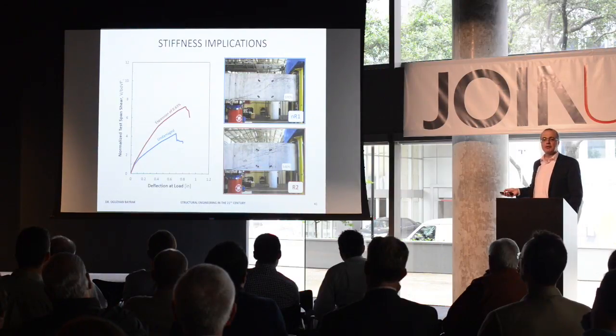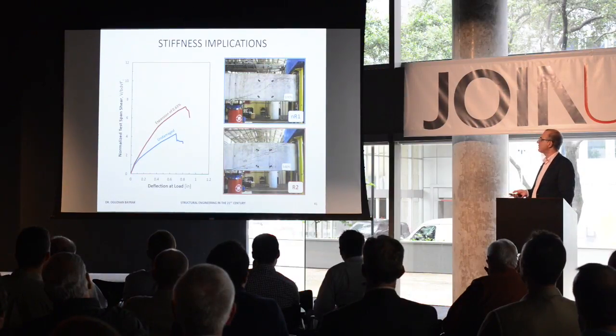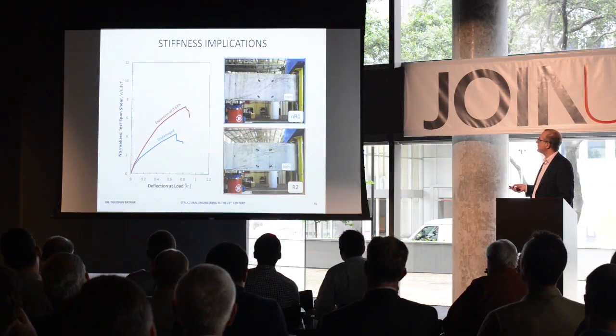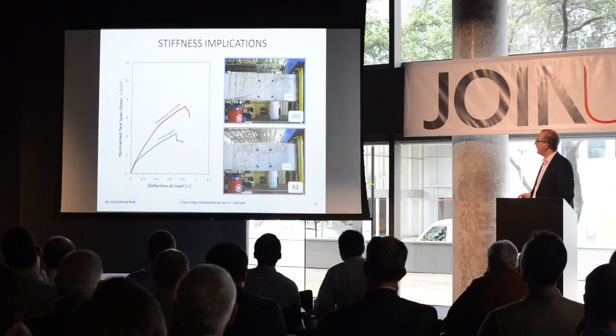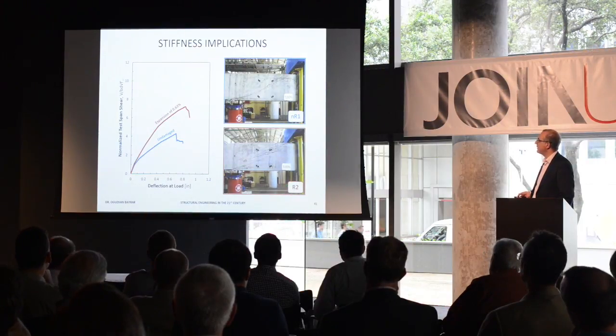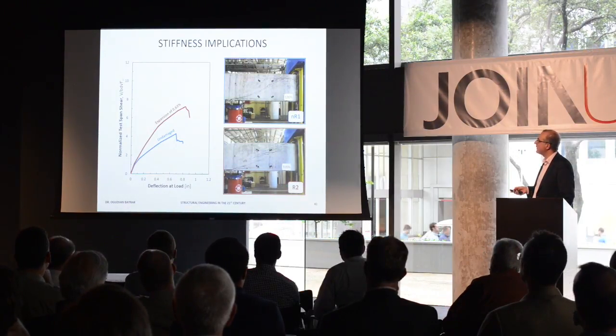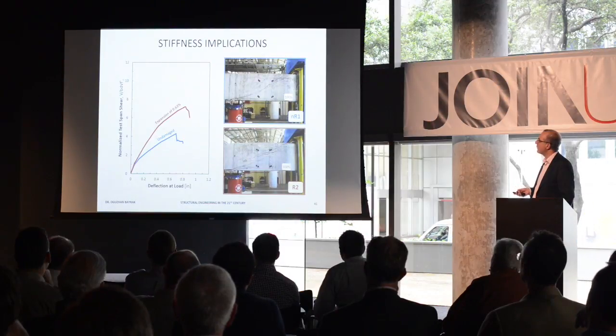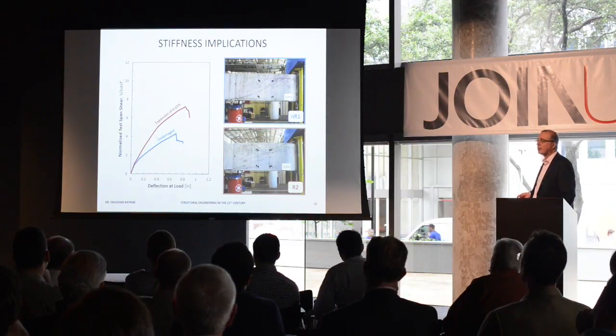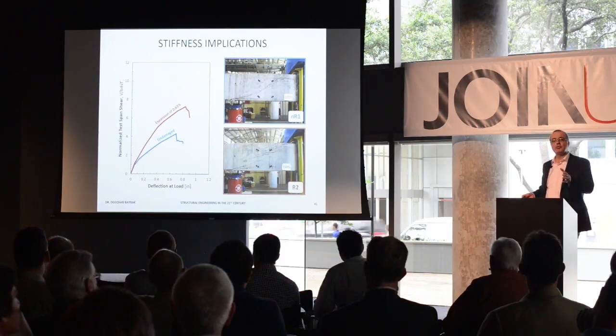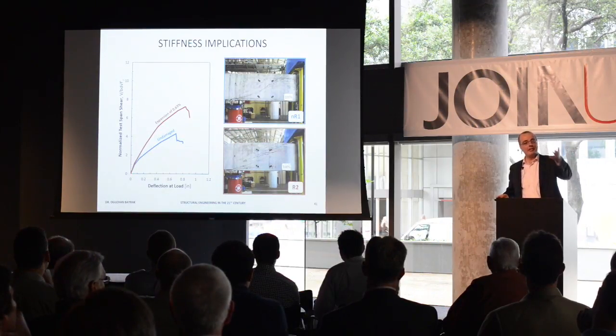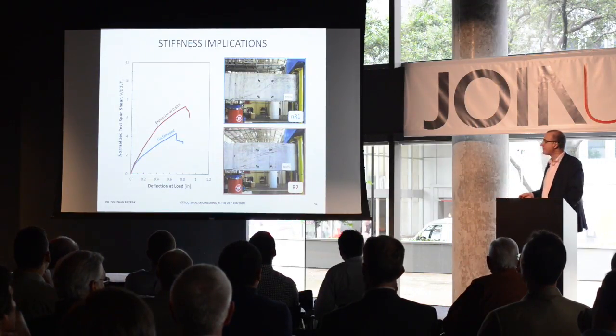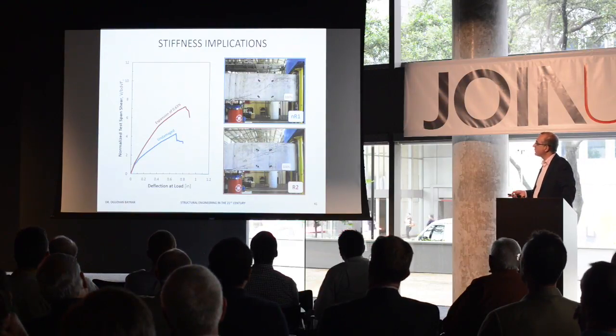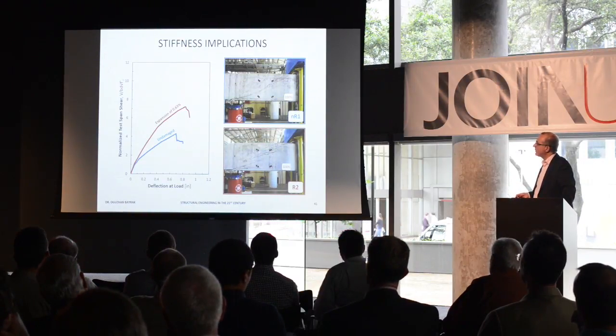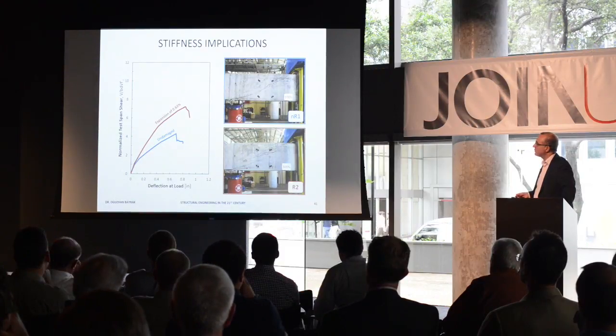Let's take a look at the structural response. Fairly interesting structural response here. Top right, we have the non-reactive beam, so that's the control beam, and we have the beam that has suffered a significant amount of ASR damage, and that would be about 0.6% worth of expansion in the vertical direction. So the stirrups have been pushed to the yield point and past that by a factor of 3. So that's a fairly significant level of expansion.